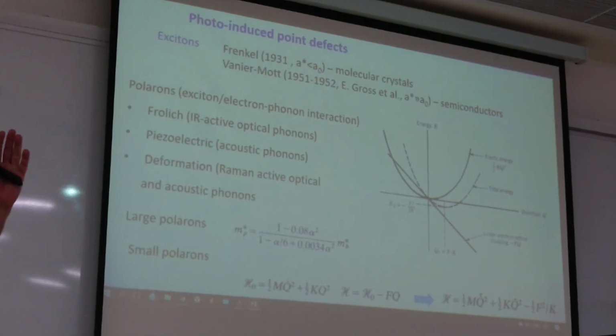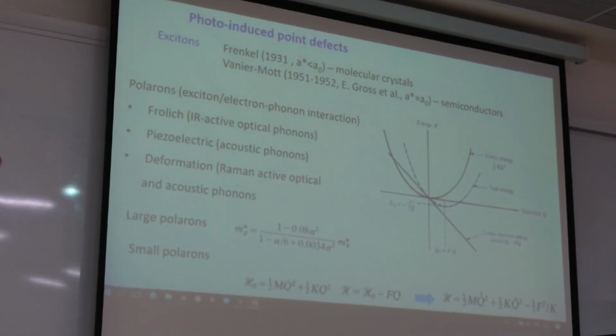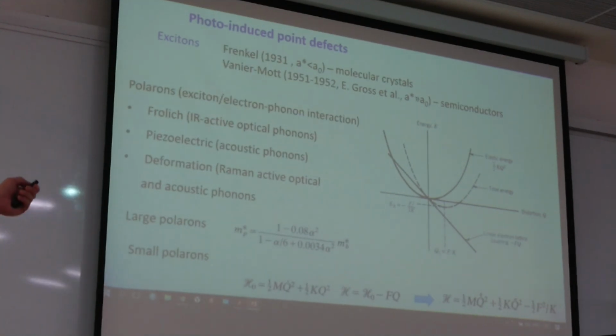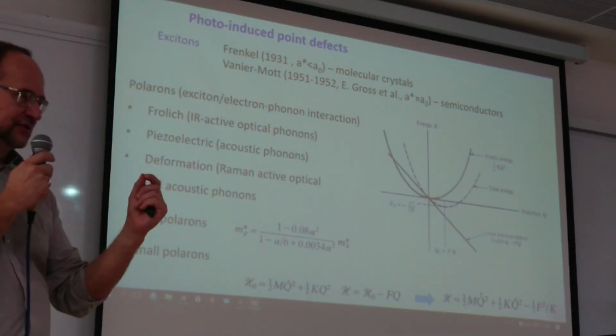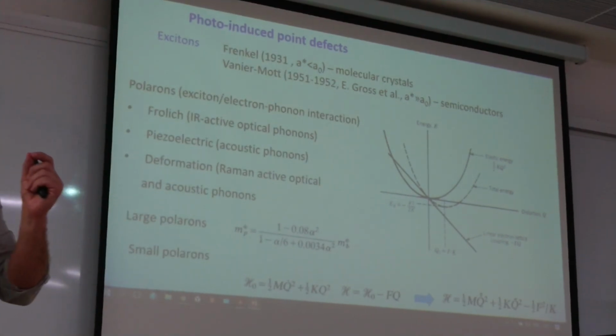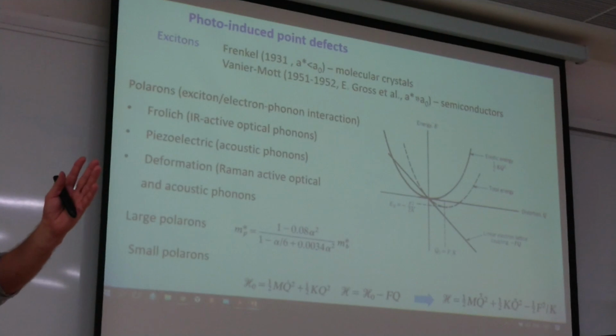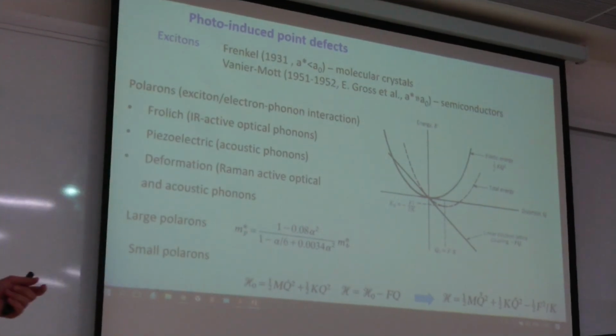Light can produce, like temperature or pressure, point defects inside materials. Typically, this is associated with excitons. There are, again, two types of excitons. Frenkel exciton, which was invented by Jakob Frenkel in 1931. It's typical for molecular crystals because the exciton is actually a couple of electron and hole, negative electron and positive hole.